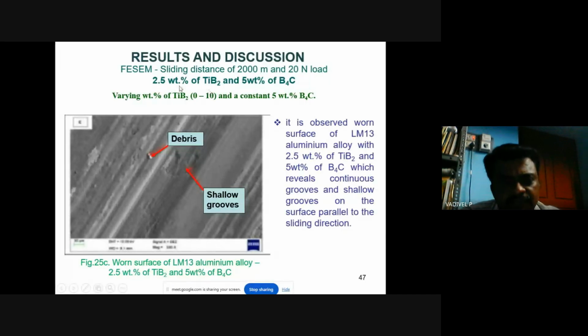This is the next level, which is 2.5% of titanium diboride and 5% of boron carbide. See here, you can see that debris and shallow grooves are observed. The surface of this 2.5% titanium diboride and 5% boron carbide specimen reveals continuous grooves and shallow grooves on the surface parallel to the sliding direction.